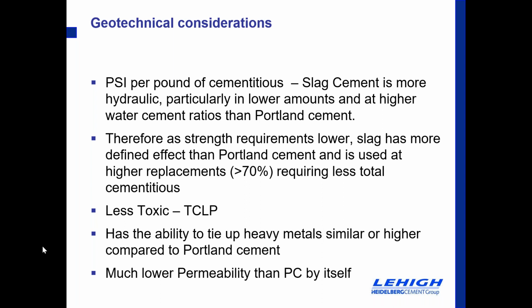So, therefore, as strength requirements lower, slag has a more defined effect than Portland cement and is used at higher replacements, sometimes greater than 70%, and of course requiring less total cementitious.